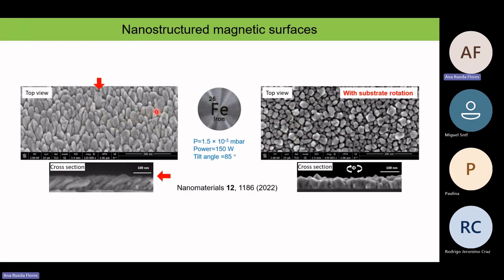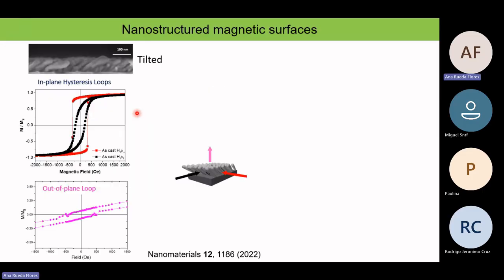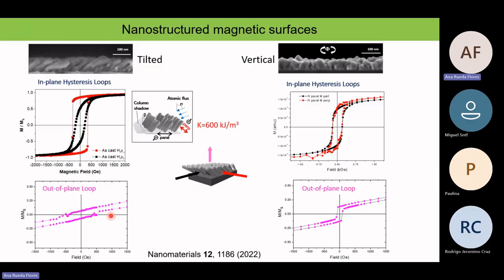You see? So that's why we have an anisotropy in this transversal direction. Now, if we focus our attention on the perpendicular hysteresis loop, it is a tilted hysteresis loop. And this is quite different to what happens when we have the vertical pillars. In this case, in the perpendicular hysteresis loop, we have in the central region some squareness, which is coming from the vertical shape of the pillars. And now the loops in the plane are equivalent because all directions are equivalent in this case.